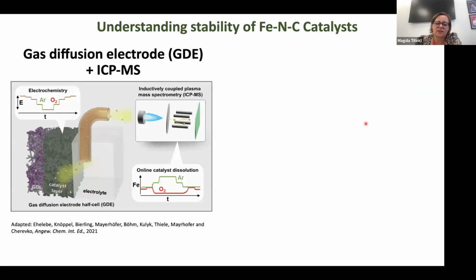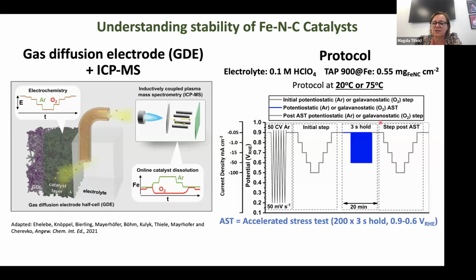That's why what we did is we coupled a gas diffusion electrode, where we have our single atom catalyst layer, with an ICP-MS to really try to understand how this catalyst degrades under real conditions. And so, of course, the real conditions are tough. Normally, a fuel cell operates at around 70 degrees, but we also did it at 20 degrees and under unsaturated oxygen atmosphere. So we used perchloric acid as electrolyte, and we really look at the degradation of the catalyst.